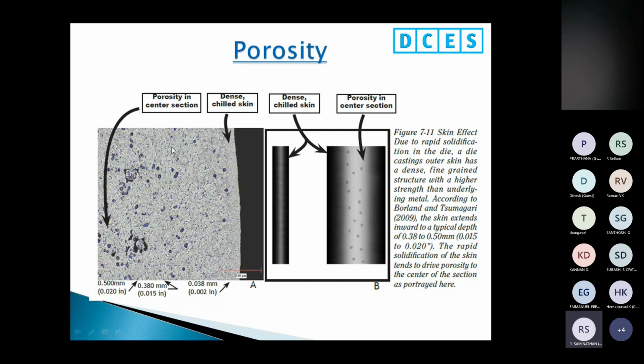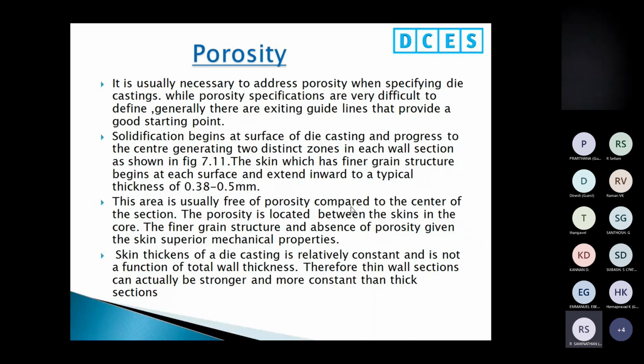So this is how the porosities form during solidification. Here there is an illustration: the dense chilled skin at the 2 walls. So what happens? The porosity is pushed to the center, so it creates the porosity. The skin, which has a fine grain structure, begins at each surface and extends inward to a typical thickness of 0.38 to 0.5 mm. That's why with the machining allowance, if you go more than 0.5 mm, the porosity will be exposed to the surface. So we only ask for less than 0.5 mm.